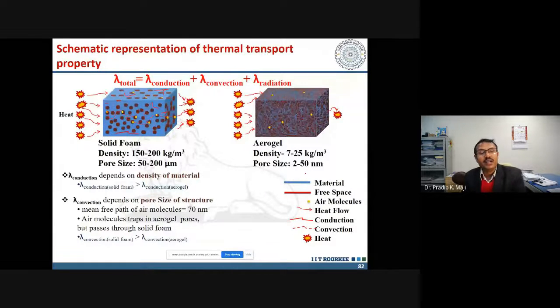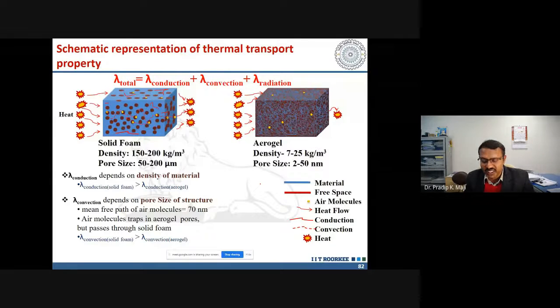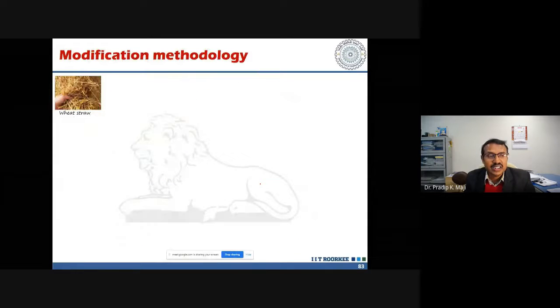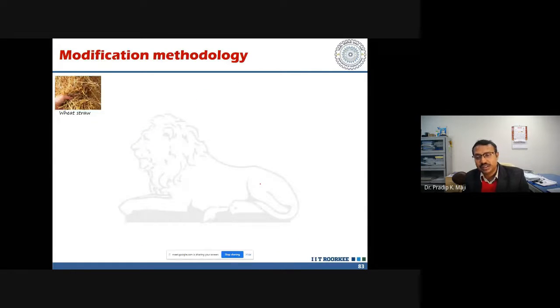This is the phenomenon I told you about, this is the mechanism. The mean free path of air is 70 nanometers, and it is not able to maintain that mean free path inside the material. So automatically the conduction, convection, and radiation, the total things, get reduced. As a result, you will get huge reduction of the thermal conductivity value. So as I told you, till now we have reached up to 25.5.